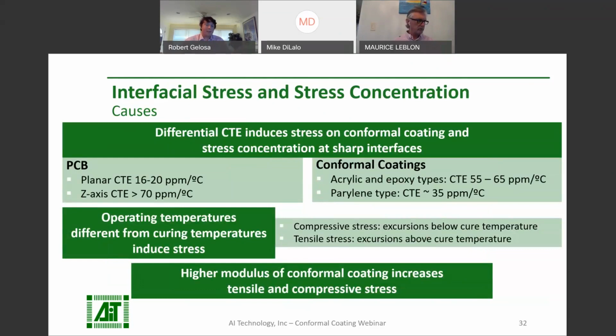No matter how much protection a coating provides, if it cracks or if it delaminates, it's not going to be effective. I bet there are those out there right now in the audience who have applied a heavy coating of acrylic and seen the results caused by interfacial stress. CTE mismatch between the coating and the board is a main culprit of stress. Just check out the CTE difference between typical acrylic and the PCB.